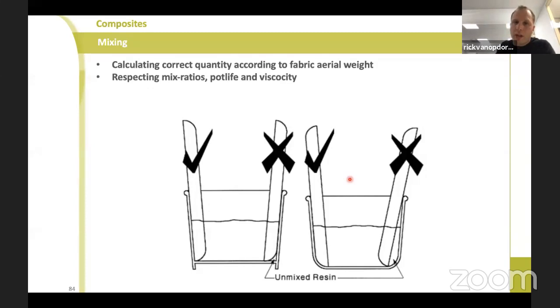So if you add too much hardener to your resin, you will create heat within the cup, and you have a big chance that you will create a fire. So you need to be very aware of the good mix ratio. Now, important to know is the pot life and the viscosity of your resin.